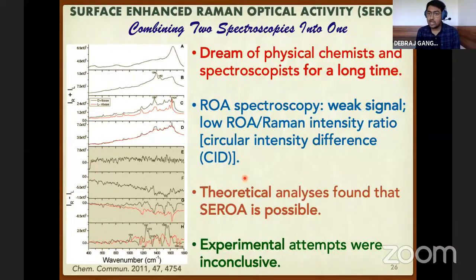If this ratio lies in a range of at least 10 power minus 4, then we may say that we have sufficient Raman optical activity signal. But you can imagine Raman itself is a very weak technique. It gives very poor signal, and Raman optical activity is even weaker by a factor of 10 power minus 4. So it's extremely weak. And is it possible to enhance it by surface enhanced Raman optical activity?